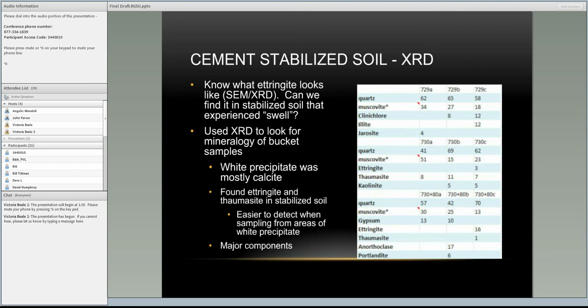And then likewise, we did the same thing with the SEM. We looked at white areas and did find needles. So these are, we confirmed with EDAX spectrum that these are ettringite needles. So this is 730. And you can see in this picture the underlying soil in there and, you know, some cracks and fracture networks in there too. This is a close-up of the 730. This is 2 microns, the scale bar down there. I know it's hard to read.